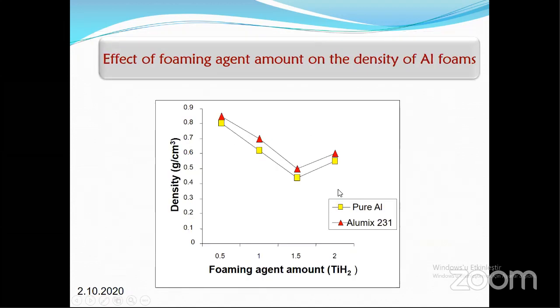This is the density of aluminum foam. This is pure aluminum, that is Alumix 231. They show a similar trend. Firstly, it is about 0.8 gram per cubic centimeter with 0.5 titanium hydride. When you increase the titanium hydride or reinforcing element amount, it starts decreasing. When you go to 1.5% titanium hydride, it came to 0.4, and then because of the collapsing of the sample, again, density rose.